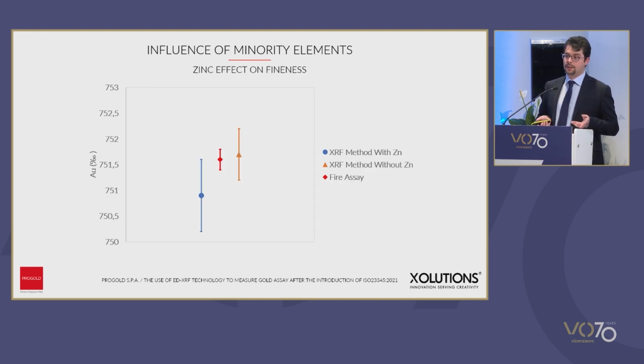And results can be seen here in this diagram. As you can see, not declaring zinc within calibration apparently improves results. And this is an instrumental limitation of the way in which curves are interconnected, because the machine receives an instruction by the operator to consider the zinc, and so the machine overestimates the presence of zinc.